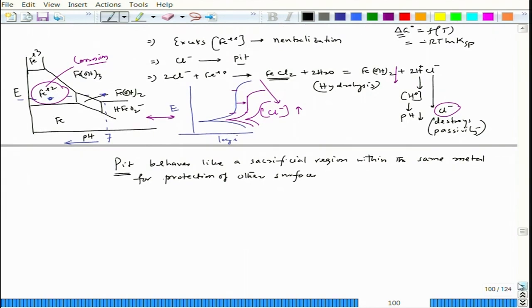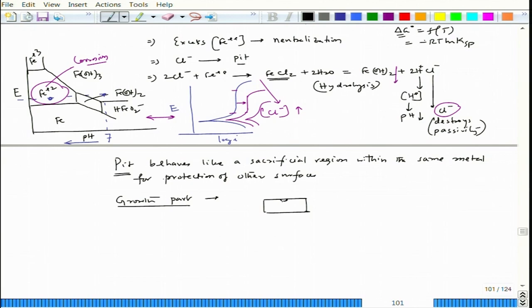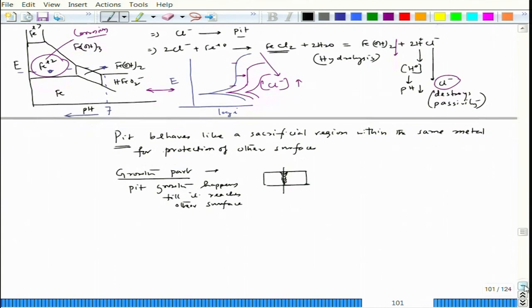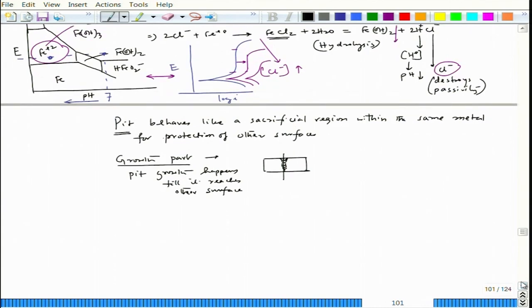The interesting part is the initiation. The growth part we just described — the growth would stop when the pit penetrates through the entire thickness of the metal. If we have a metal cross section and a pit starts and grows, finally a leak happens and the growth stops. So, the pit grows until it reaches the other surface. This is the typical nature — even in the crevice case, crevice stops when the entire metal cross section is perforated.